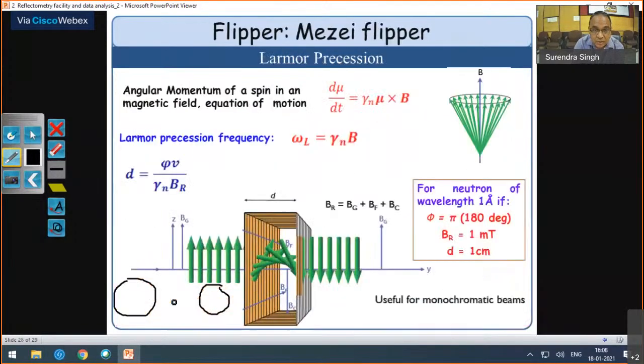I was showing this, you can see here. If you apply a uniform magnetic field, if the magnetic field is not uniform, you have to apply the magnetic field perpendicular to the neutron spin. The spin should be perpendicular to this, because then only it will precess by pi degrees. Otherwise, it will make like this here. If it is at some angle, it won't give you that, it will precess around that, but it should be at 90 degrees. B should be at 90 degrees to the spin.